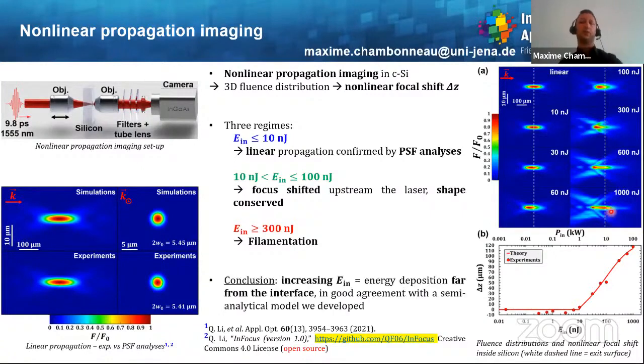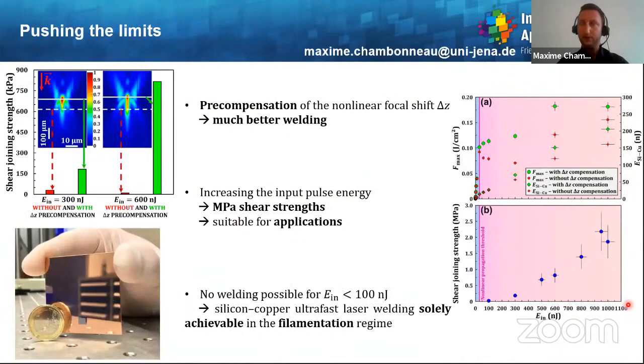So the conclusion of this is that when you increase the input pulse energy, the energy deposition will be farther from the interface, which is in very good agreement with a semi-analytical model that we have developed, which is represented by the solid lines here on this graph. So now that we know the reasons for the nonlinear focal shift, and we have characterized the evolution of this nonlinear focal shift as a function of the input pulse energy, let us try to push the limits a little bit.